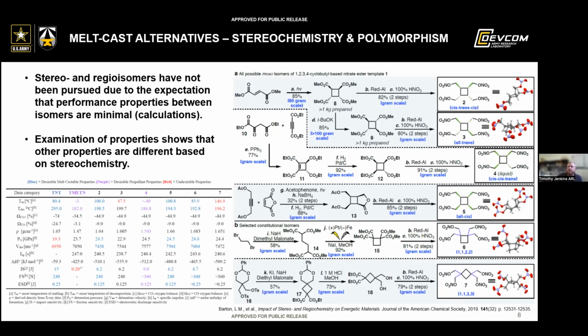And in fact, you can, and this is what their paper talks about. Looking at these different materials, you can see that you don't see any difference in structure: same groups, same atoms, and a different arrangement. So what you see when you do the calculation is essentially the same energy output, but you do see vastly different material properties. This one's a little bit counterintuitive to traditional energetic material design, but potentially has a good application in this area.